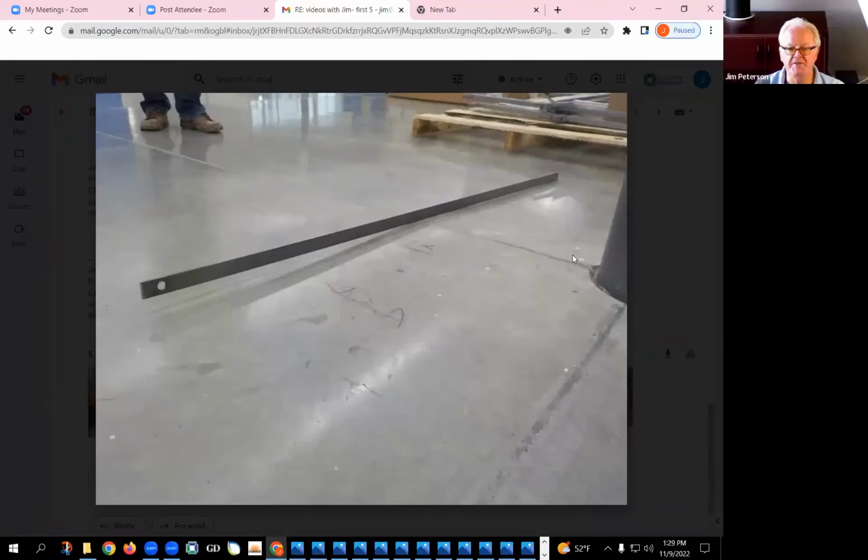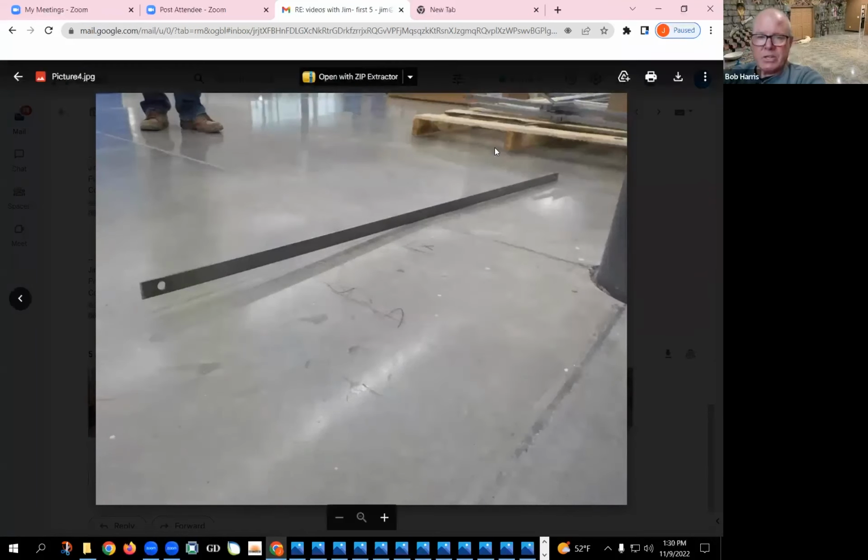That's a smart idea. I hadn't thought of that. Good call. Yeah, and another thing, Jim, this gets back to the first episode that we did with regard to mix design. If we know that a slab is being polished, oftentimes we'll assign specified FF, which stands for floor flatness, and FL, which stands for floor levelness, measurements to the floor. And so we have certain standards knowing that the slab is going to be polished. For example, an FF of 50 and an FL of 35 is a standard specification, knowing that we're going to do either a cream finish, a class A, or a salt and pepper class B finish.